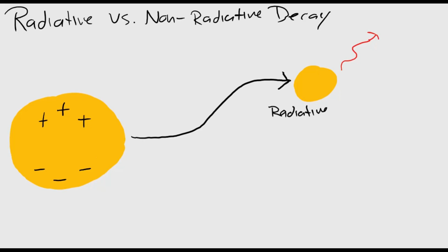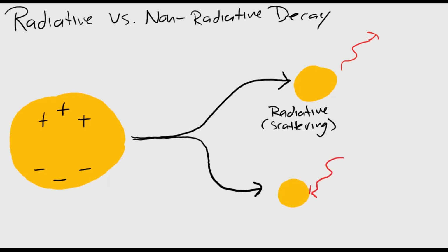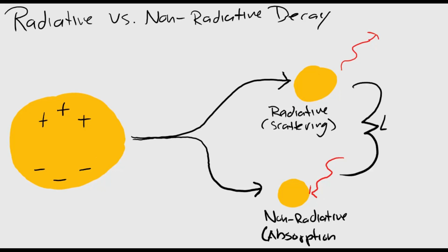Metal nanoparticles scatter light efficiently, allowing radiative properties to be easily isolated from their net optical response on a single particle level. And there are many techniques that characterize scattering. Recording pure absorption of single nanoparticles is more difficult, however, primarily because the signal from a single nano object is typically too small to be measured against the high background signal, and increasing the size of the object to enhance absorption also increases the scattering cross-section, which then greatly overwhelms the absorption cross-section. One way around this difficulty is to use a thermal intermediate to measure absorption.